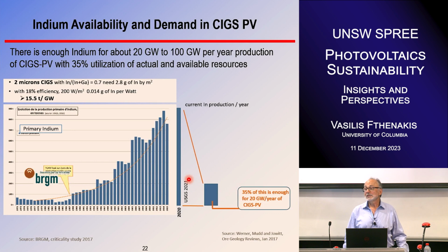Now, the indium story is a little different. It's substantially different. One, the supply is already mature. We don't expect to have any new sources or any higher material recovery in indium. And two, there is a lot of competition for indium from thin film displays and all of this, even small cell phones and so on. There is a lot of competition. The CIGS technology cannot go away from indium. If you use indium in ITO, you could substitute indium tin oxide with fluorine tin oxide, for example. But for CIGS, they are actually stuck with indium.